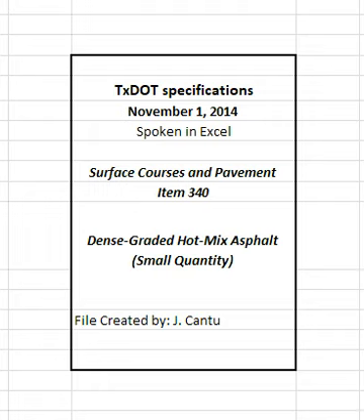The plans may require or disallow specific mineral fillers. Provide mineral filler, when used, that is sufficiently dry, free-flowing, and free from clumps and foreign matter as determined by the engineer, does not exceed 3% linear shrinkage when tested in accordance with TEX 107E, and meets the gradation requirements in Table 3.